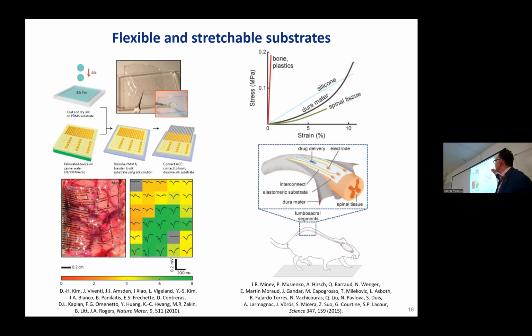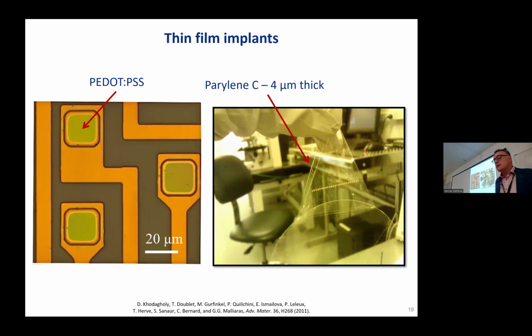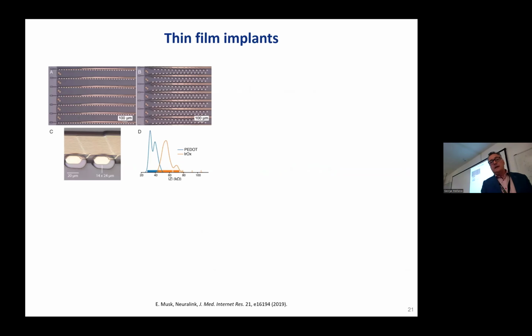So combining this flexible and stretchable with microfabrication, you can make electrode arrays that are very thin, flexible polymers. And in this case, with enough mechanical strength to handle their own weight, with making very small electrodes to get very high resolution recordings from the surface of the brain. These are to be placed on the surface. And then this is what Elon Musk's company does, Neuralink. They use a similar technology to make devices that get pushed into the brain. So these look like linear arrays with small electrodes shown here. Again, the size is of the order of tens of microns, commensurate with the size of the soma of a neuron. So they can record single neuron activity.